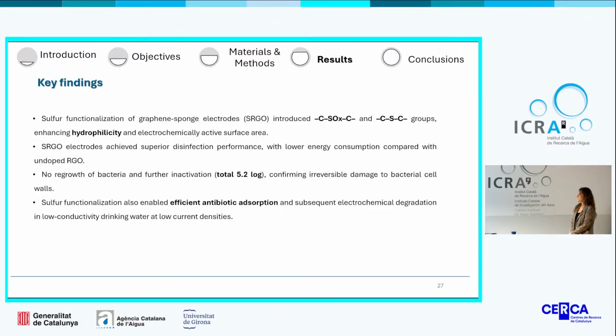The key findings of this study were: the sulfur functionalization in the graphene sponge led to the creation of different sulfur oxide containing groups, which enhance the hydrophilicity of the electrode and the wettability of the material. The SRGO electrode achieved a better removal in comparison with undoped reduced graphene oxide with lower energy consumption. In both cases, SRGO and RGO as an anode, no regrowth of bacteria was observed, and in the case of SRGO, 5.2 log removal was achieved, confirming also the irreversible damage of the bacteria. Then sulfur functionalization also led to a good adsorption of the antibiotics and subsequent electrochemical degradation.